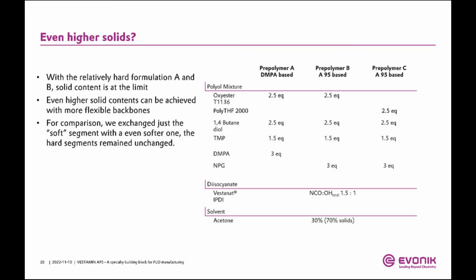So the question is then, as I said, we have not yet optimized or tuned this system to A95. We just took the polymer as it came and just exchanged the A95. Can we now go even to higher solids? Well, when we stay with this relatively hard formulation, you remember we had very high amounts of hard components and we had a relatively short 1000 molecular weight polyester. The solid content is already at the limit, as we would say, but if you go for higher solid contents,